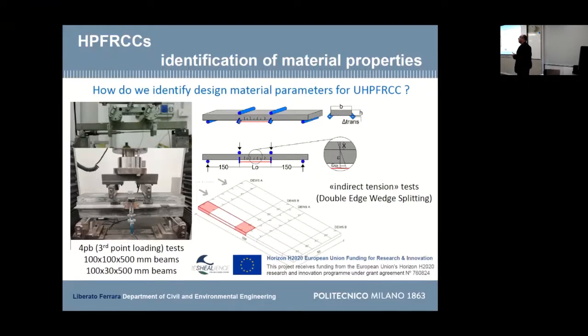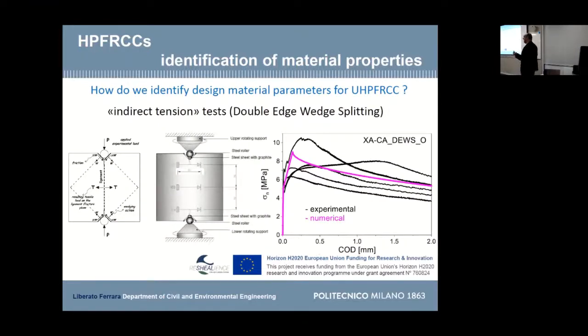We performed a 4-point bending test in this case because we wanted a zone in which we could have multiple distributed cracking. And then we also developed a test methodology, an indirect tensile test methodology, which is this one. We call it the double edge wedge splitting. You have these square tiles, we cut grooves and notches, and then we apply through some devices a compression force. So the principle is the same as the Brazilian splitting test. What do these grooves do? Well, they deviate the compression forces far from the ligament, so that, as we checked with finite element analysis, we have on the ligament a pure tensile stress state.